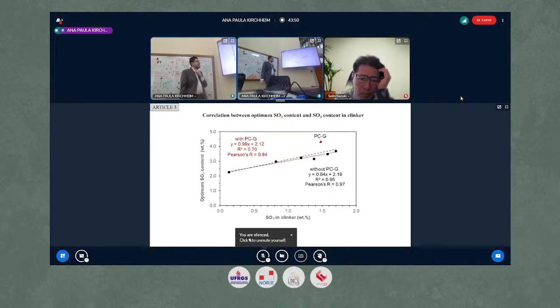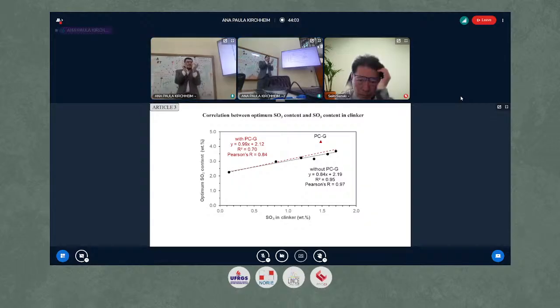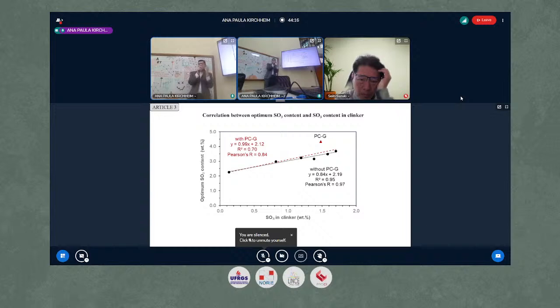So here, PCG is the exception, but we see a very strong linear correlation between the optimum total sulfate content and the clinker sulfate. What does this mean? It means that if I have more sulfate in the clinker, the optimum total sulfate will be higher. So it doesn't make a lot of sense at first, but what this is telling us is that not all of the sulfate in clinker is participating in the reactions to control the aluminate reaction.